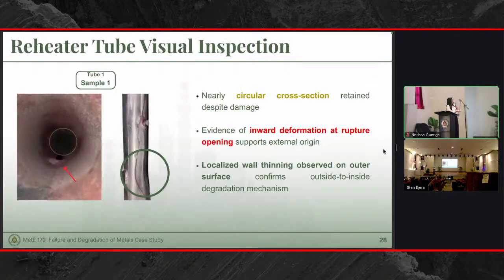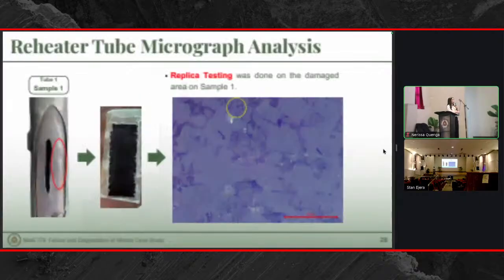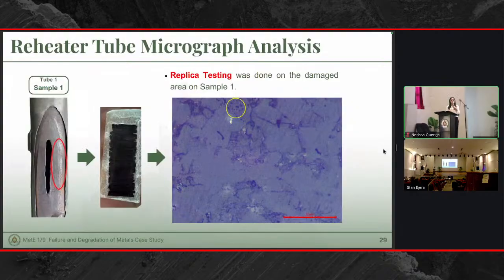We can also notice that there is inward deformation at the rupture opening, further supporting the external origins of the failure. We conducted replica testing adjacent to the rupture, and we can see that the sample retained its original microstructure, which means that there are no overheating mechanisms involved. However, there is some evidence of spheroidization, which could possibly be because of the steam impingement.